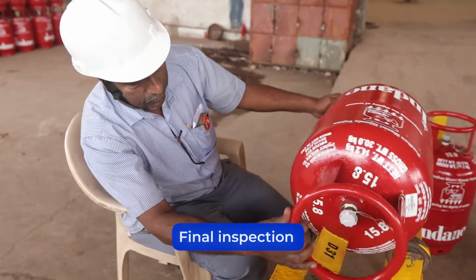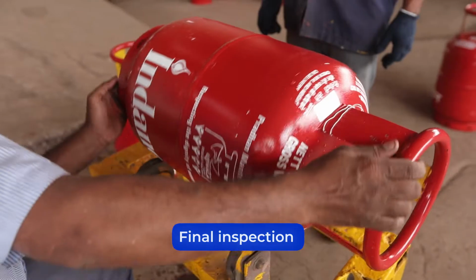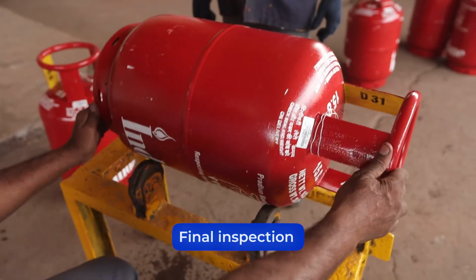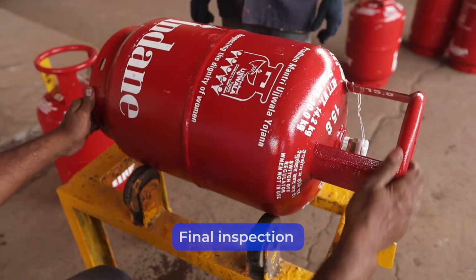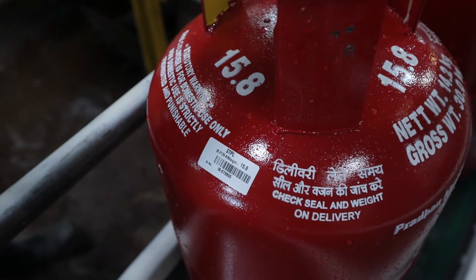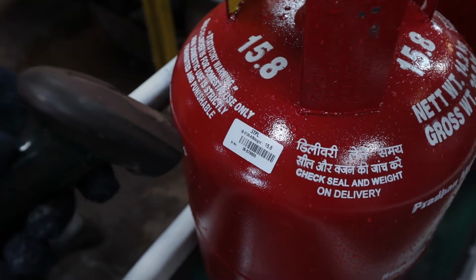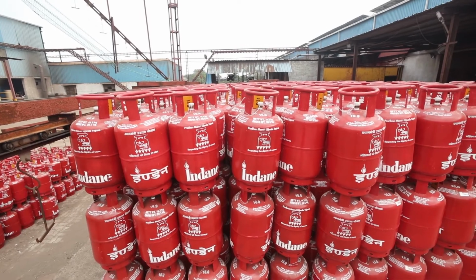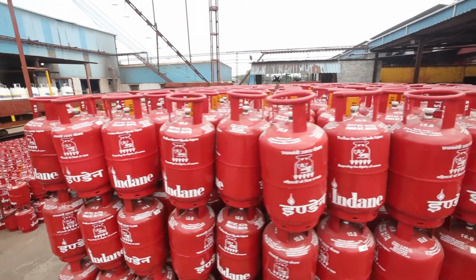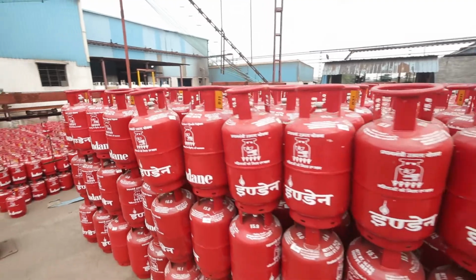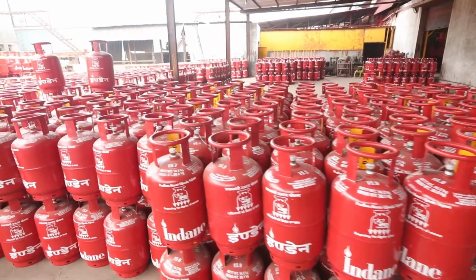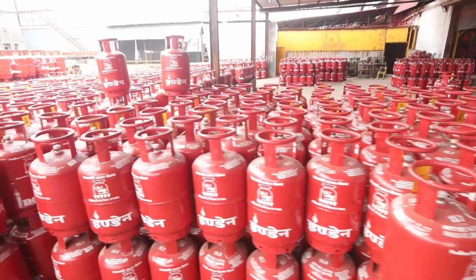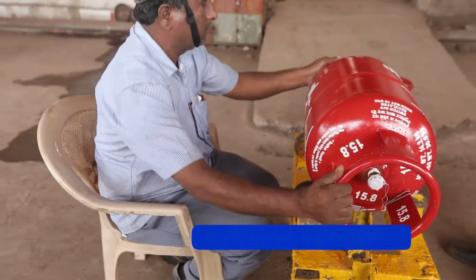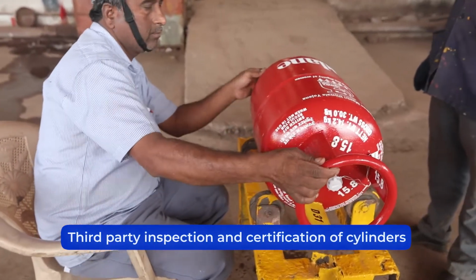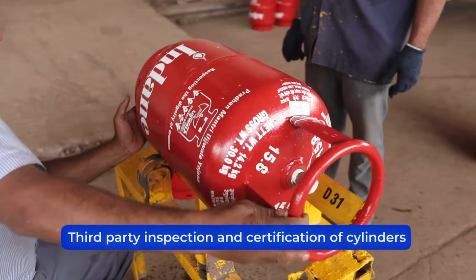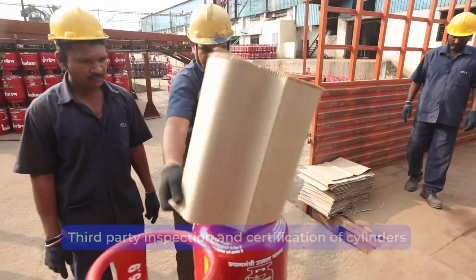Here's the final inspection. After the air evacuation process, cylinders are inspected for any defect of stenciling or other visual defects and scanning barcode after pneumatic. Such approved cylinders are then stacked batch-wise for BIS inspection and certification. Cylinders are randomly drawn for performing acceptance tests and burst tests. The same is carried out by a third-party inspection agency.